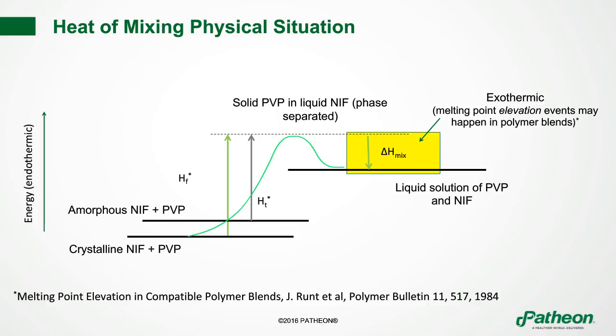Now, it may be the case that in some systems you actually see an endothermic event where upon mixing you have to actually add in more energy to get the system to mix. Well, when that happens, you probably have a situation where you have an unstable dispersion that's going to just phase separate and recrystallize, at least the drug part of it will recrystallize into domains, and then you've effectively defeated the purpose. And we can measure that too, and we can look at that from a simulation perspective to try to understand that this polymer drug combination is not going to make an effective dispersion.